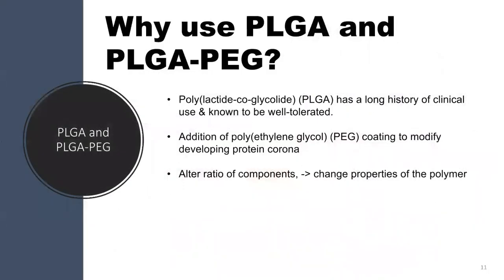So the nanoparticles that I'm currently working with are PLGA, usually known as either polylactic co-glycolic acid or polylactide co-glycolide. We're particularly using this one because of its long history of clinical use and the absence of side effects from using it. The additional polyethylene glycol coating enables us to modify the developing protein corona. And furthermore, if we alter the ratio of lactic and glycolic acids in this polymer, we can also start to modify some of the behaviours of the polymer itself.